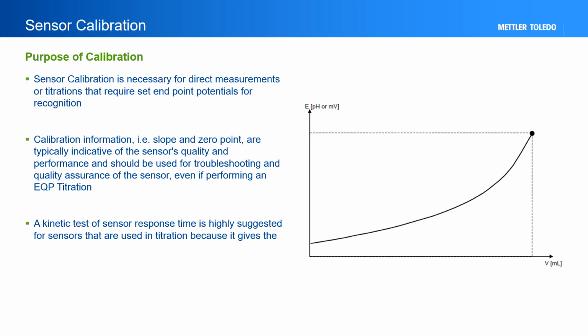Not all titration sensors require calibration. If performing direct concentration measurements, such as pH, or a titration having an endpoint established based off a concentration value, such as a titration to pH 8.3, the used sensor requires calibration. An equivalence point titration, which utilizes an inflection point determination based off the first or second derivative of the generated titration curve, does not require a sensor calibration.